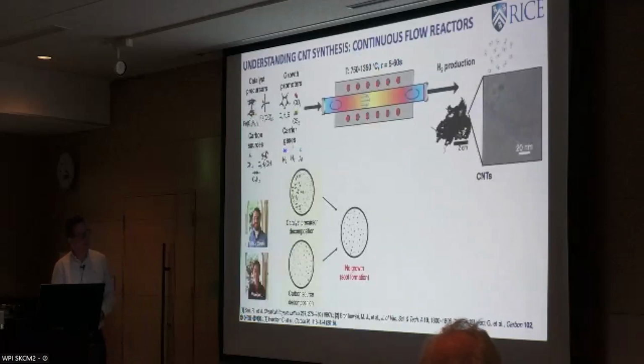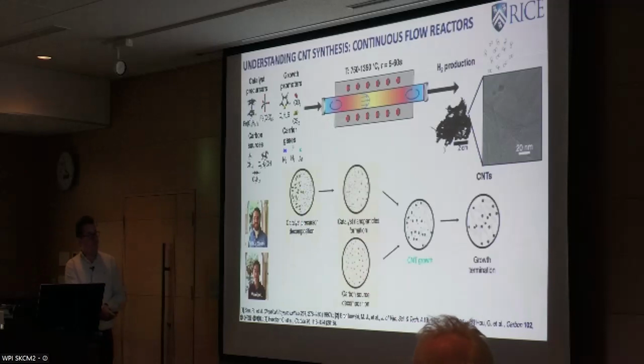This is happening because we understand better how to make these materials. For example, there are very interesting processes. When you make these materials, you typically use tubular furnaces where you put in precursors for a catalyst, which are metal particles, and gases that bring in your hydrocarbons. And you have two concurrent processes. One is that your catalyst precursor has to decompose and make the catalyst, and the carbon source has to decompose. If these two happen at the same time at the beginning of a reactor, you don't get growth because the carbon source is decomposing before the catalyst is ready, and you get soot formation.